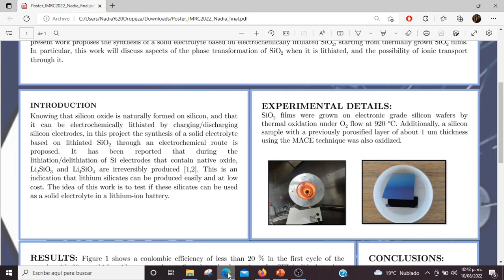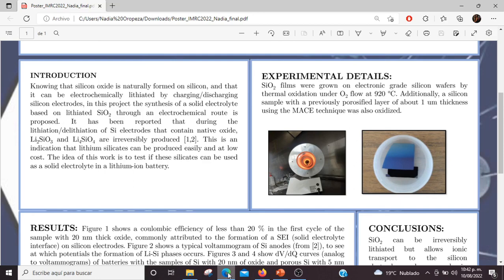Knowing that silicon oxide is naturally formed on silicon and that it can be electrochemically lithiated by discharging silicon electrodes, in this project, the synthesis of a solid electrolyte based on lithiated silicon oxide through an electrochemical route is proposed. It has been reported that during the lithiation of silicon electrodes that contain native oxide, lithium silicates were formed. This is indication that lithium silicates can be produced easily and at low cost. The idea of this thesis work is to test if these silicates can be used as a solid electrolyte in lithium-ion batteries.